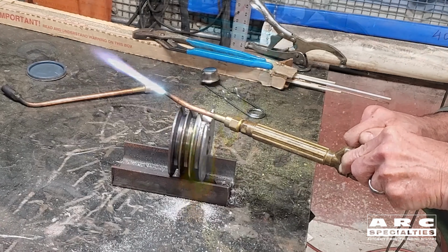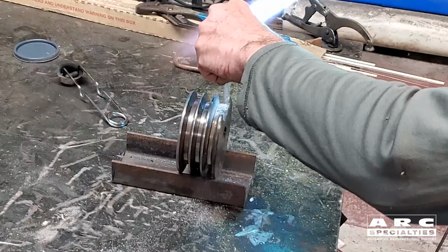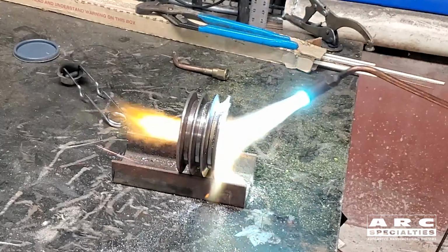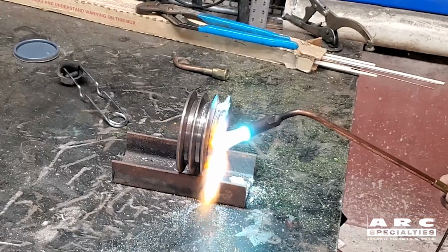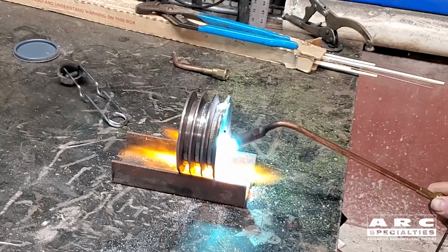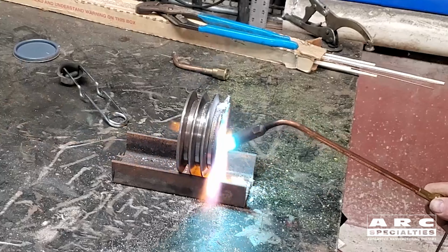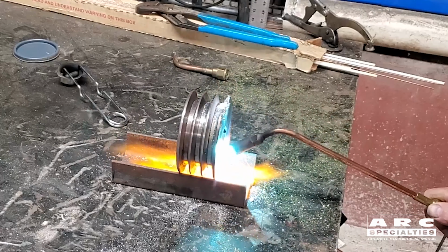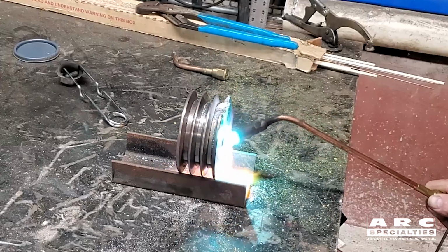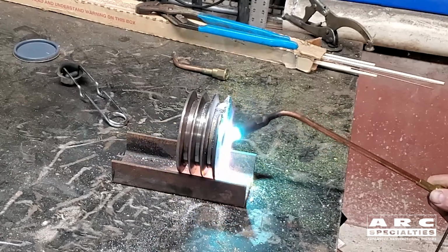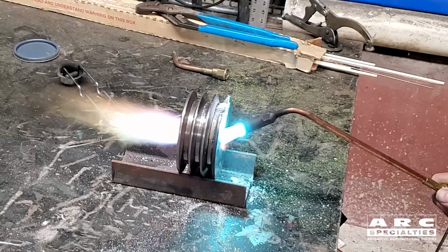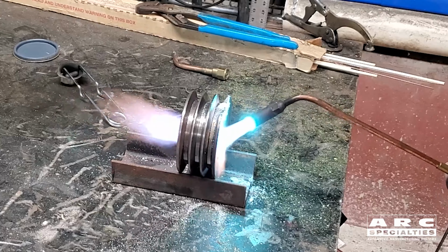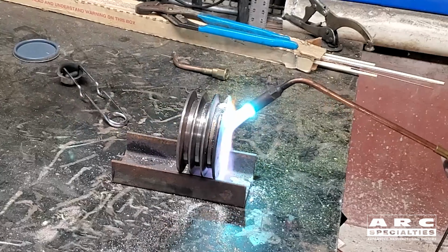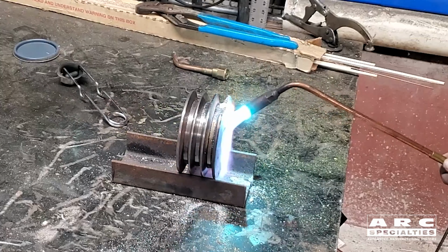So I've been applying flux to this through the entire operation. That's to prevent this surface from oxidizing as we heated up the part. So I'm continuing to apply flux, I'm continuing to apply heat. Unfortunately, all I had was a double-aught tip, which is a bit small, so this is going very slowly, but you can tell when the base metal is up to the right temperature, because when you apply the brass, it wets and flows much like soldering. So you know exactly when the metal is at the proper temperature.